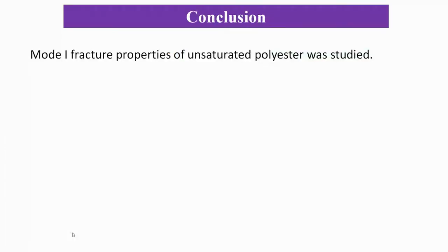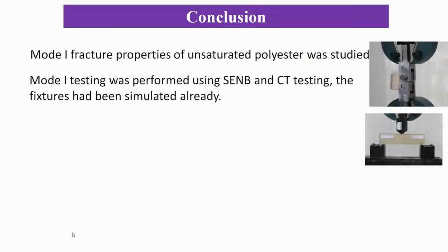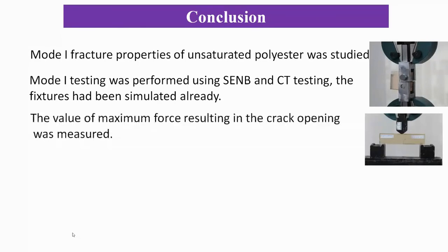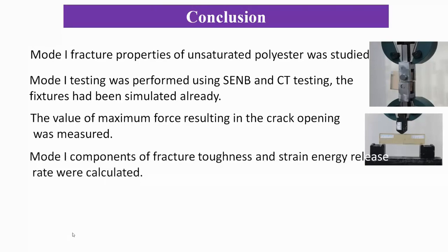In summary, in this work, we studied the mode 1 fracture properties of unsaturated polyester. This was performed using SENB and CT testing. The fixtures were first simulated and then manufactured. The values of maximum force resulting in crack opening were measured. Mode 1 components of fracture toughness and strain energy release rates were calculated using these two methods.